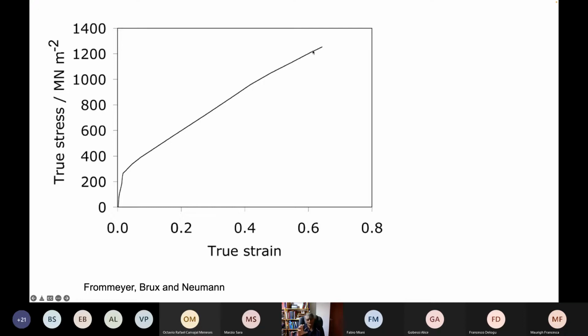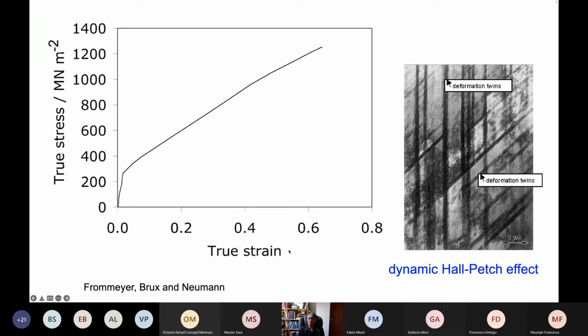So what is the reason we don't get an early plastic instability? Just like in normal steels, you don't get to 60% elongation at this level of strength. Well, what's happening is something known as a dynamic Hall-Petch effect. In other words, the formation of the mechanical twins effectively reduces the grain size of the austenite. So as the twins form, the effective grain size in the Hall-Petch equation is decreasing during the course of deformation, and that is what gives us the work hardening that prevents an early onset of plastic instability.